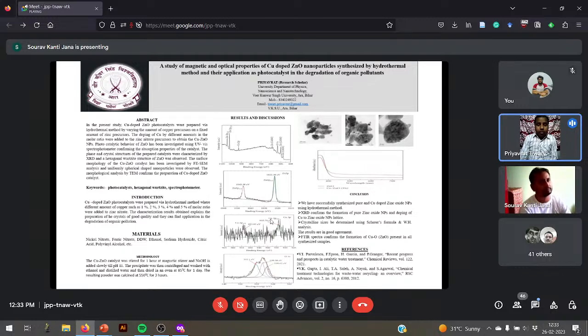Photocatalysts such as TiO2, ZnO, ZnS, SnO2, and WO3 have been used widely in wastewater treatment. Due to high stability, low cost, non-toxicity, great photoelectric conversion efficiency, and controllable material, ZnO is the most effective, efficient semiconductor photocatalyst. As a result of its wide bandgap energy, narrow visible light absorption, and high recombination rate of photo-generated electron-hole pairs, ZnO alone is limited. To overcome the limitations of ZnO, it is combined with other narrow bandgap semiconductors, and there are also reports on doping with metals and non-metals to improve the catalytic efficiency of ZnO. As a result, the photocatalytic efficiency of ZnO will be improved due to the separation of photo-generated electron-hole pairs and improved visible light absorption of ZnO.